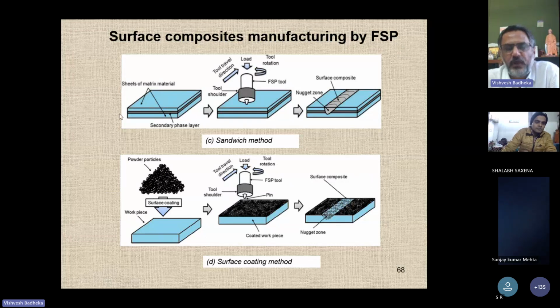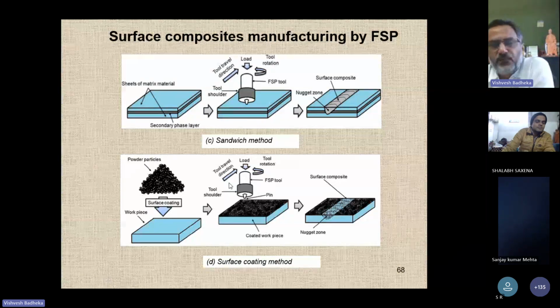In the sandwich technique, you have the powder between the layers. You see here, between the two metallic sheets, you have a reinforcement, and with the help of a direct FSW tool you can develop the metal matrix composite. And in the fourth method, you can put the powder directly on the surface and develop a surface coating with the help of an FSW or FSP tool. So these are the four techniques.